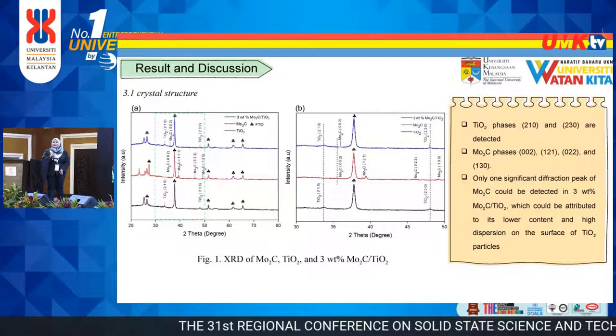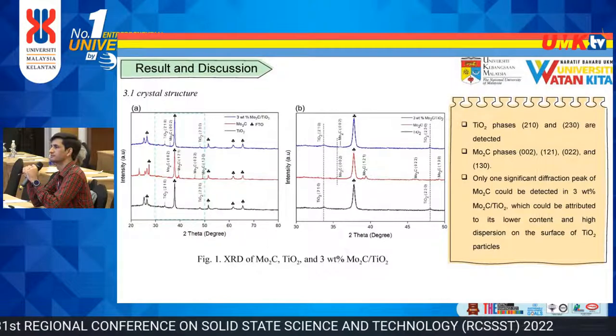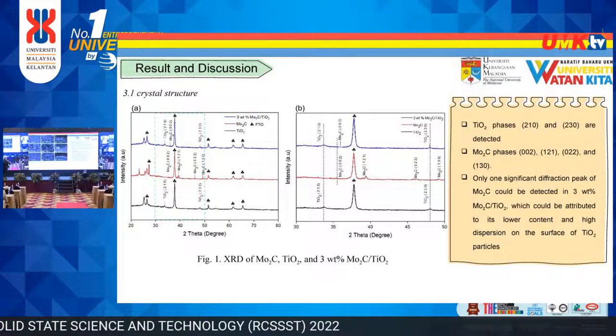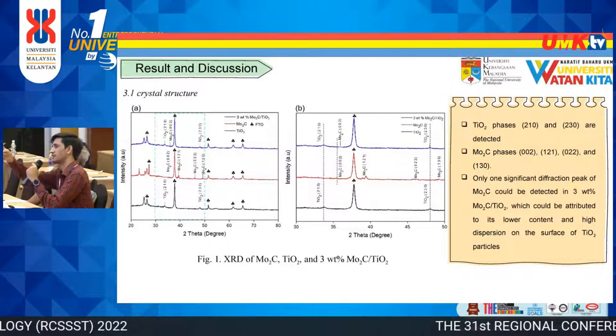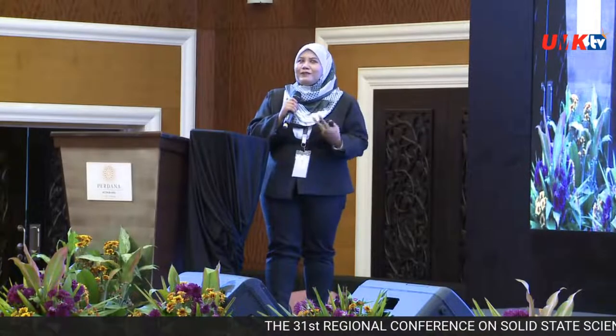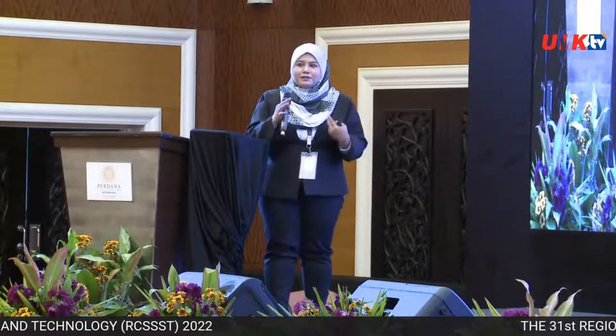Okay, and I want to see your absorption UV-Vis results. Can you please explain what you were claiming about the absorption here? You were explaining something about the absorption of the material a while ago. Absorption, yes. So what happened when you combine those? The absorption is increased, because TiO2 only absorbs in the UV region, while molybdenum carbide absorbs from the UV until the visible light. So when TiO2 and molybdenum carbide are combined, it improves the region of absorption of TiO2 and also decreases the band gap of TiO2. So when you combine both Mo2C and TiO2, do you see any absorption in the visible region?